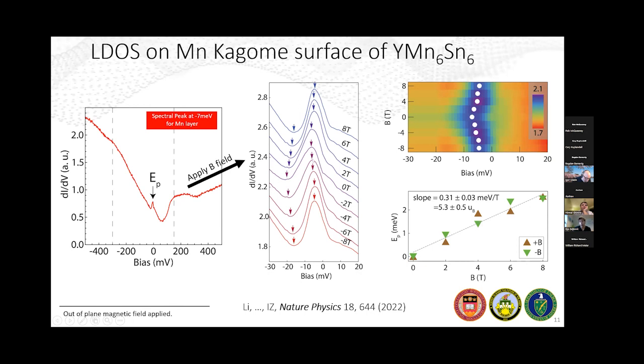And what we found is that here on the right, I'm showing this peak zoomed in to a narrow energy range. As a function of magnetic field, this peak does not split. If this was some kind of spin degenerate state, one would expect the peak to split into two as you apply the magnetic field. But in both cases, with the field applied along plus c-axis or minus c-axis, the peak just moves. And we can calculate how much this peak moves as a function of applied magnetic field. The velocity of this dispersion is something like 0.3 millielectronvolts per Tesla. This is a much higher dispersion velocity than what you would expect from a conventional spin g-factor, which would be maybe 5 to 10 times smaller than this. And again, the fact that the spectral peak does not split leads us to believe this is a spin polarized spectral feature.